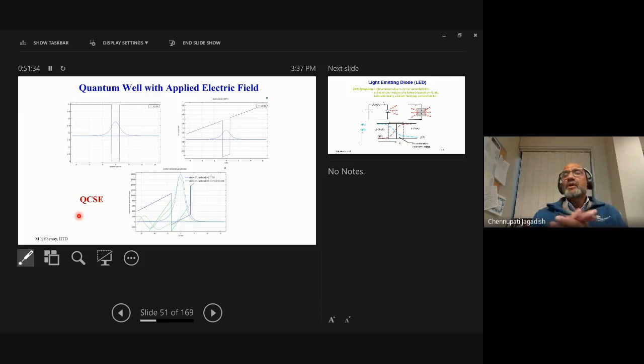You're creating a band bending in a quantum well, which changes the peak at which the absorption takes place. By doing that, you're able to switch on and off. The laser is coming in and going to the modulator, and the modulator is electrically switched on and off. So you're sending the information using the modulator, and that can send high speeds of information. Sometimes directly modulating lasers beyond certain frequencies, like beyond 40 gigabits per second, becomes much more challenging. But modulators can modulate much faster because you keep the laser in a stable state.